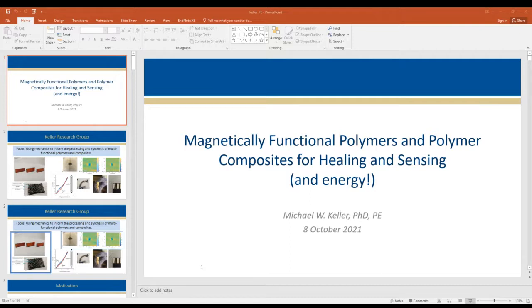So the first thing that we did with this was to just recreate that structure. Our goal here is to take microcapsules that we make through a really simple process, and we incorporate a nanoparticle. So an iron oxide nanoparticle, right? Iron oxide comes in a lot of different flavors. This is a magnetite-maghemite form of the iron oxide, which is also like lodestone, right? That's that mineral, so it's magnetic or paramagnetic. We were able to make microcapsules where we incorporated that. You can see the capsules here stuck on a magnet. And it's also kind of cool, if you look here, you can see this is a razor blade that's been magnetized. You can watch all the nanoparticles come to one side inside the individual microcapsule, right?